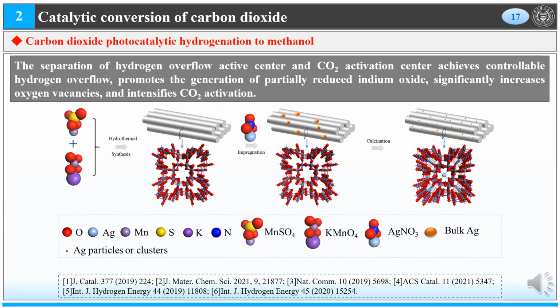The separation of hydrogen overflow active center and carbon dioxide activation center achieves controllable hydrogen overflow, promotes the generation of partially reduced indium oxide, significantly increases oxygen vacancies, and intensifies carbon dioxide activation.